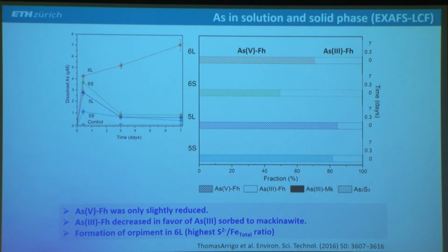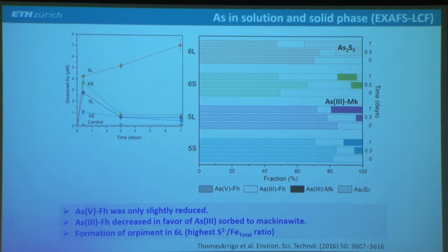And after the spike and incubation, we saw that the arsenic speciation in the flocks also changed. We saw some formation of arsenic(III) adsorbed to mackinawite. And in this sample, which was the highest sulfide to iron ratio, we also saw some arsenic sulfide mineral precipitating, that's orpiment.